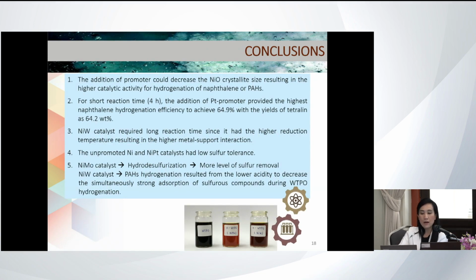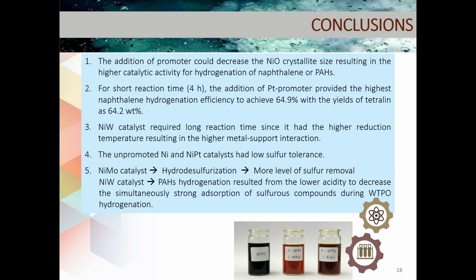In conclusion, the addition of the promoter could decrease the nickel oxide crystalline size, resulting in higher catalytic activity for the hydrogenation. And the platinum provides the highest naphthalene hydrogenation efficiency, but in the presence of thiophene, the nickel platinum is not good. And nickel tungsten requires a long reaction time because it shows the higher reduction temperature, resulting in higher metal support interaction. And the unpromoted nickel and the nickel platinum also show low sulfur tolerance. Nickel molybdenum catalyst shows the higher hydrodesulfurization, while the nickel tungsten catalyst prefers the PAH hydrogenation.